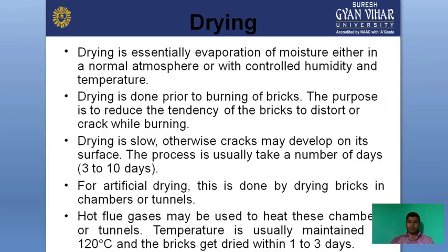Drying is essentially evaporation of moisture either in a normal atmosphere or with controlled humidity and temperature. Drying is done prior to burning of bricks. The purpose is to reduce the tendency of bricks to distort or crack while burning. Drying should be slow, otherwise cracks may develop on the surface. The process usually takes 3 to 10 days. For artificial drying, bricks are dried in a chamber or tunnel at approximately 120 degrees, and bricks get dried in 1 to 3 days.